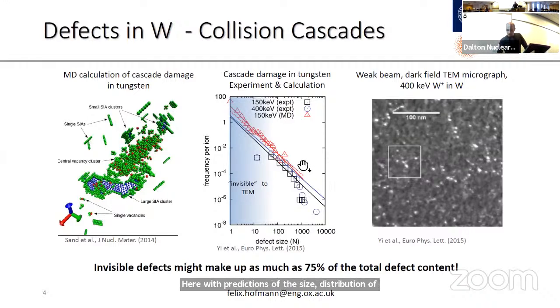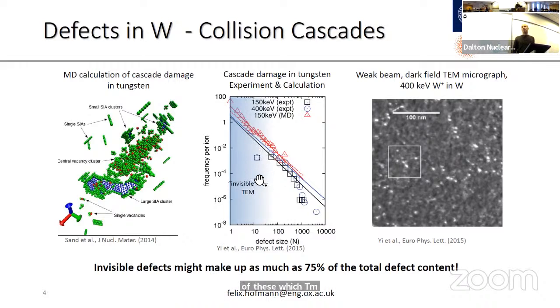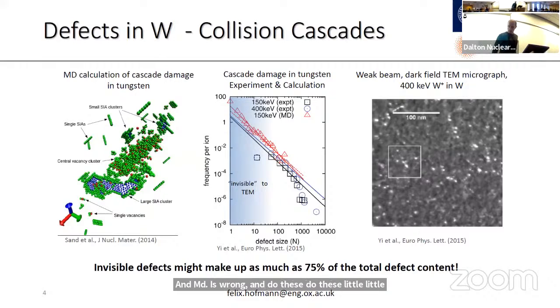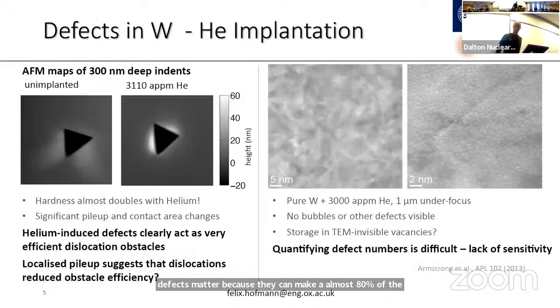And something that you notice is that MD predicts all of these tiny defects here, right? Which TEM doesn't seem to be able to see. And the question is, well, are they actually there? Is it just that TEM can't see them, or they're actually, as this would suggest, just not in the material, and MD is wrong? And do these little defects matter? Because they can make up almost 80% of the total defect population.